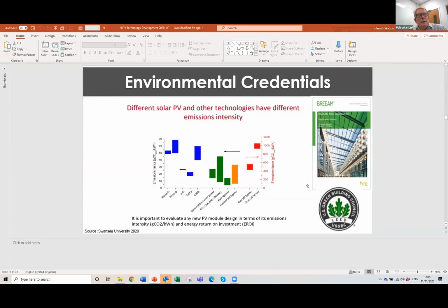In terms of the environmental credentials for thin film materials, we produce in the amorphous silicon and the cadmium telluride sector, which is aSi and CdTe on there. As you can see, there's significantly less embedded carbon in their production return than there is in conventional PV. Equally, if you look at the other side of the scale there, which is the red ones for gas and coal, they have a completely different scale because their carbon emission is so much higher than the renewables. So it's an interesting one. This is recent research from Swansea University.